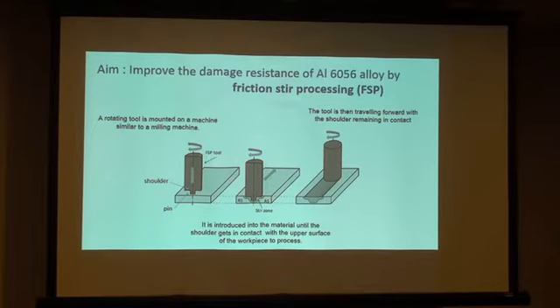It's composed of a shoulder and a pin. You introduce the tool within the material until it gets in contact with the upper surface of the plate, and then the tool is just traveling forward, and you've got this process zone. What we did is that we performed overlapping passes. So the number of passes is just the number of times that you have processed the material at the same place.